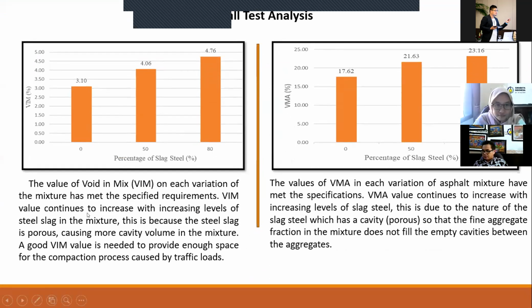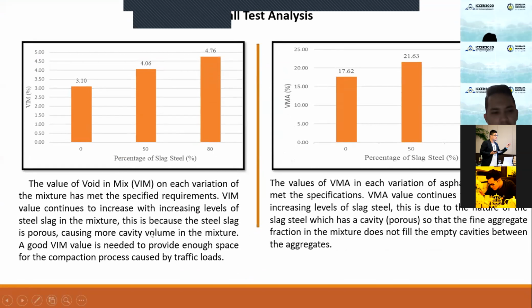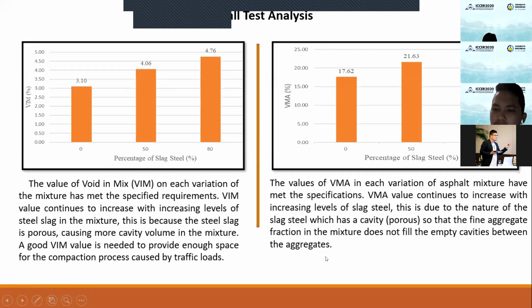The VIM value continues to increase with increasing level of steel slag in the mixture. This is because the steel slag is porous, causing more void volume in the mixture. A good VIM value is needed to provide enough space for the compaction process caused by traffic load. The VMA values in each variation of asphalt mixture have met the specification. The VMA value continues to increase with increasing level of steel slag. This is due to the nature of the slag.